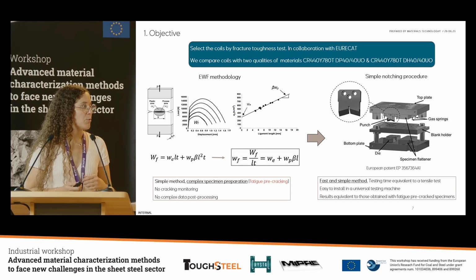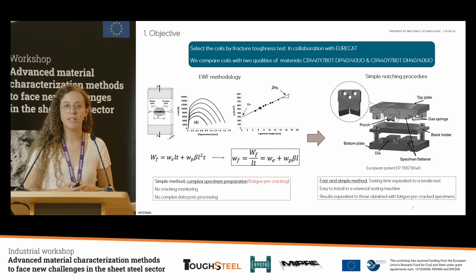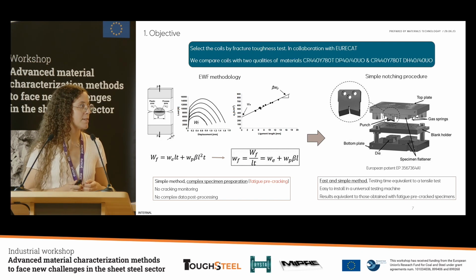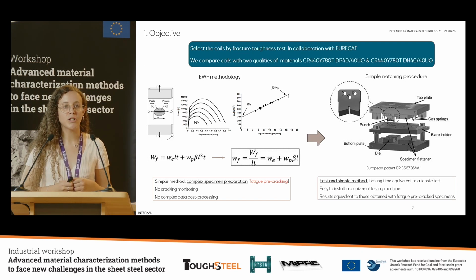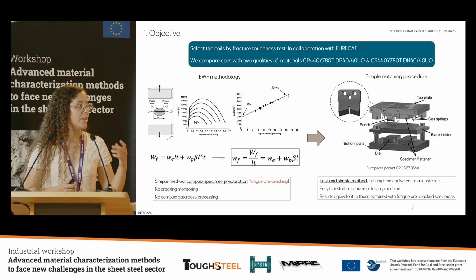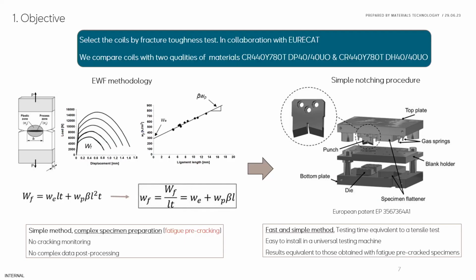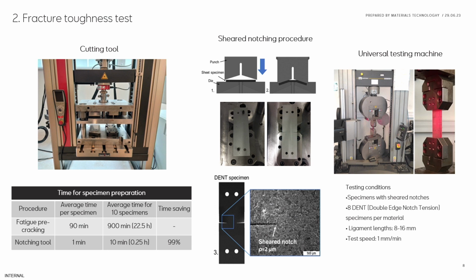Then what we proposed to them was to use a new tool that we have developed here in Eurecat, which is a method to create sharp notches in a specimen in just a few moments. One critical aspect to measure fracture toughness is the radius of the crack tip. It needs to be very small so that the measurement doesn't depend on the radius of this crack tip. So with this method, we can perform a fast and reliable measurement of fracture toughness. We can see here a description of the tool and how it works.